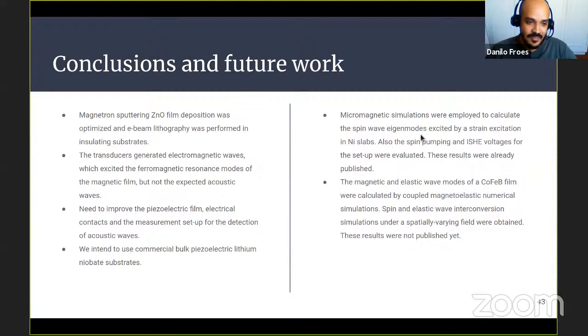Okay, so just to conclude, I'm not going to read it all, you can be calm. Basically, for the experimental part, we did the ZnO film deposition by magnetron sputtering. We could do the electron beam lithography, but the transducers do not generate the acoustic waves we were expecting. Maybe they generated them, but they were very much attenuated. We couldn't do experiments with the acoustic waves yet, but they did excite the ferromagnetic resonance modes, the k equals zero modes, which we were not expecting. Maybe there is some current leakage there.